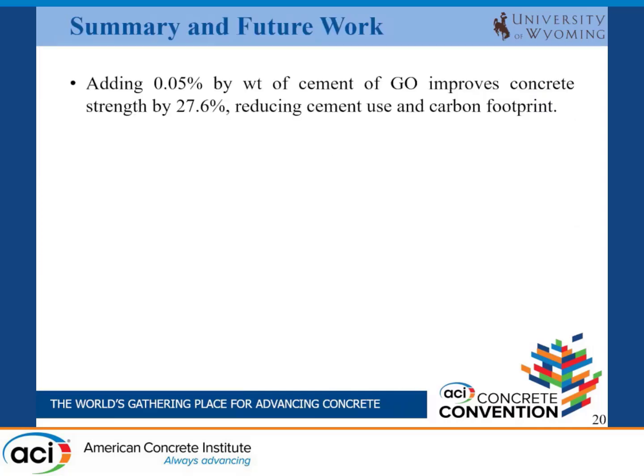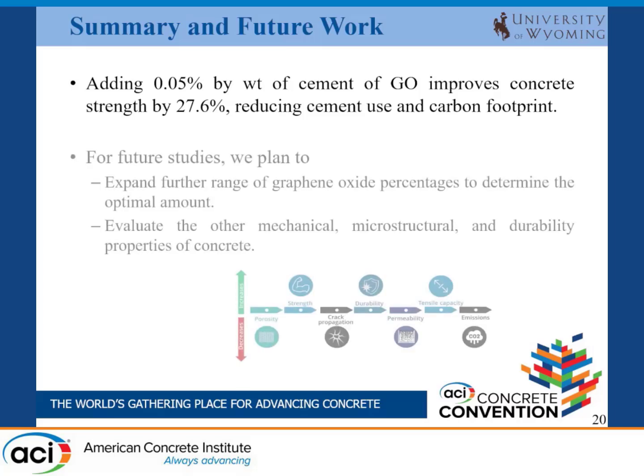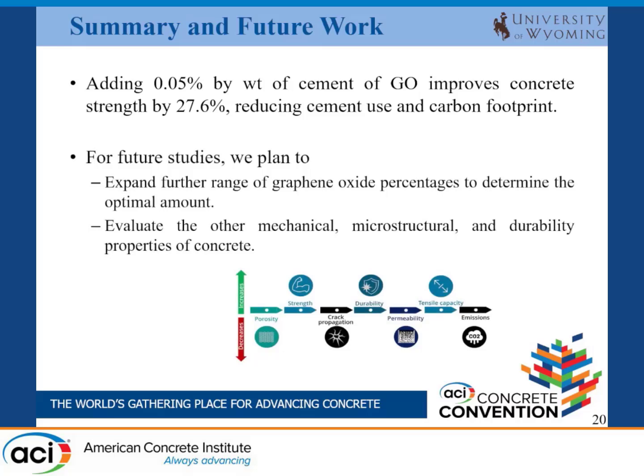So in summary, we can conclude that the optimal range of our graphene oxide is between 0.05 to 0.1% in the concrete, to get high strength, like 27.6% higher than the control mix concrete. This is an ongoing project, and we are also currently working on other mechanical properties, microstructure and durability of concrete, and we want to introduce some other additives into the concrete to see whether this graphene oxide affects the concrete properties or not.